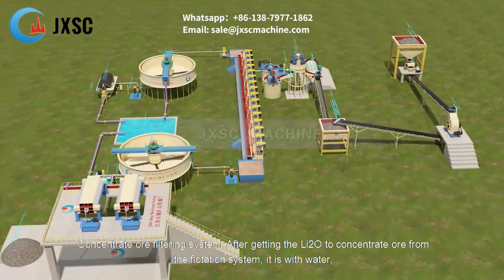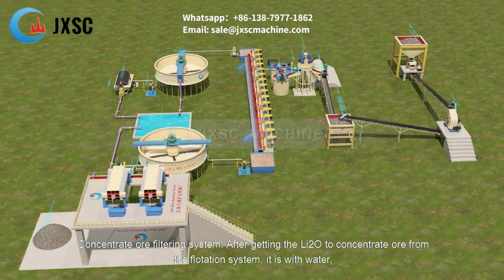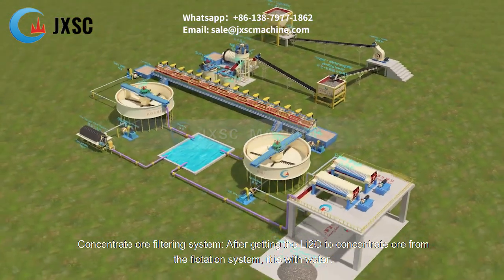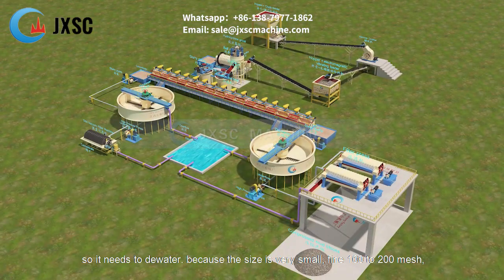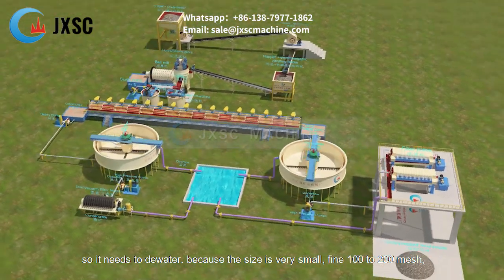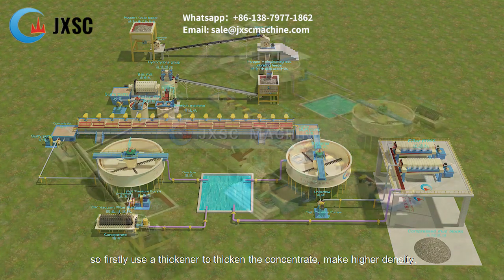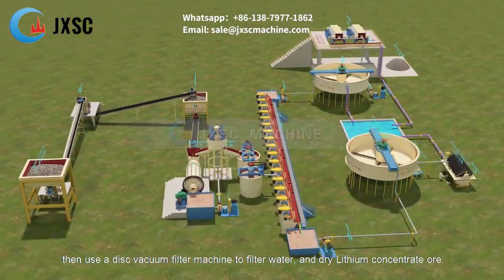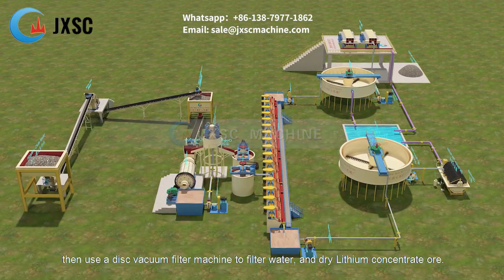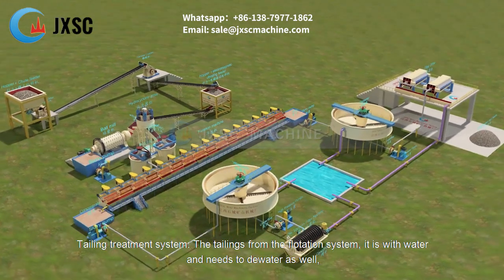Concentrate ore filtering system. After getting the Li2O concentrate ore from the flotation system, it is with water, so it needs to dewater. Because the size is very small, fine 100 to 200 mesh, firstly use a thickener to thicken the concentrate, make higher density, then use a disc vacuum filter machine to filter water, and get dry lithium concentrate ore. Tailing treatment system.